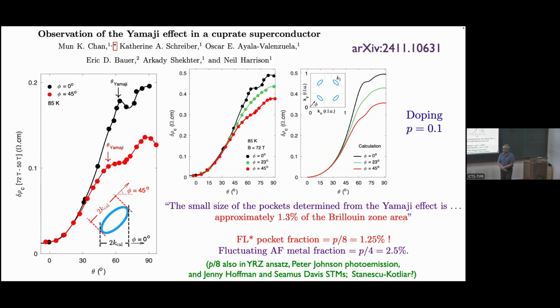Yeah. Any other spectroscopic measurement, what would be the signature of this effect? Well, I will talk about the predictions for photoemission. Then there's neutron scattering. Neutron scattering would predict that there are lots of spinon continua at higher energies. There is evidence for that, but I won't talk about that here. We're right now writing a paper making detailed predictions for what should appear in neutron scattering. Yeah, there are of course thermodynamic measurements. The spin susceptibility will be that of a small Fermi pocket. So that's the first place. NMR was the first place the pseudogap was seen, by a dive in the spin susceptibility that many of the models can get.